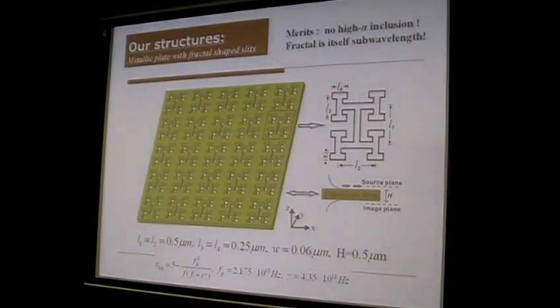Borrowing the idea from the fractal concept, our structure is actually a metallic plate drilled with fractal-shaped slits. This is a perfect metallic plate, and we drill some kind of fractal-shaped slits. This is a 4-level fractal, and this is the slit, inside which air is filled. Yeah, I do not want to go into the details of this structure. Why did we adopt this idea? Because we understand that a fractal is itself subwavelength, so that we do not need a high index material to lower the response of the whole structure. So that's why we think that this structure perhaps can support well-defined surface plasmons.